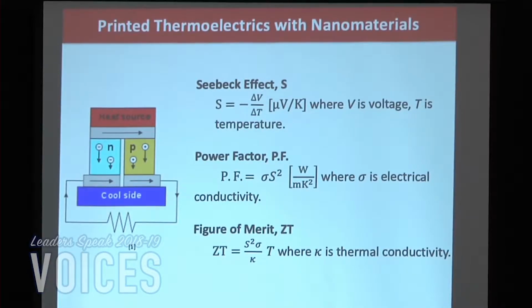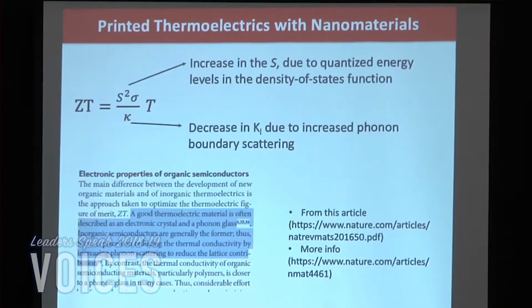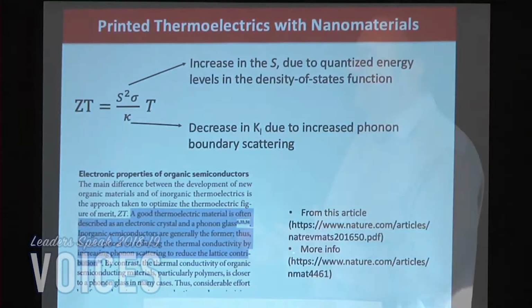Here are some of the factors involved, the figure of merit. If we look at the ZT value, that's the value that shows how efficient it is. So thermal conductivity is in the denominator. You want to decrease that for these materials, and then you want to increase the Seebeck coefficient and the electrical conductivity. So those are some of the parameters that we're looking at and trying to increase. And we can do that in a number of ways using these telluride-based nanowires. They have low thermal conductivity and a high electrical conductivity. So they're kind of unique semiconductors in that way.